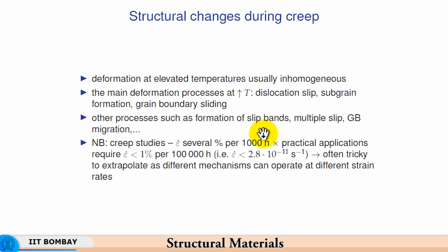So, if you have very small grain size initially, during the entire creep process there can be some growth in the grain size, but on the whole the creep resistance, the strength under creep, comes down with increase in temperature and increase in grain boundary area, because the grain boundary becomes weaker at high temperatures. Therefore most of the deformation gets concentrated in the grain boundaries, and so the resistance to deformation goes lower and lower as the grains become finer under creep conditions. So we need as large a grain size as possible so that creep is resisted.